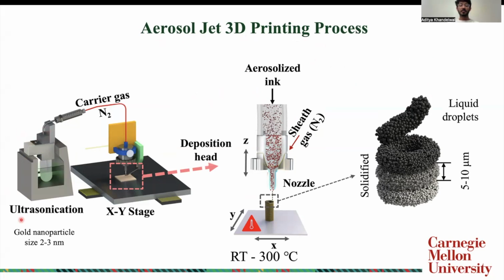First, the ink is aerosolized by the ultrasonicator. The ink is loaded with nanoparticles of choice. In our case, we use 2 to 3 nanometer gold nanoparticles. The ink is carried to the deposition head using carrier N2 gas, which is then deposited on the XY stage. The XY stage is temperature controlled so that we can control the temperature of the process. As the ink deposits, it solidifies and turns into a 3D structure.